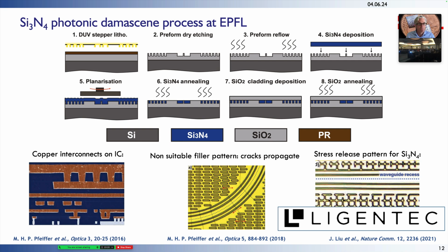Yeah, I mean, in theory. If you etch all the way through, you always see a limit. I didn't put it in the slides, but we have detailed this in papers that we published, very detailed follow-ups from Martin Pfeiffer, who developed the process in my group, in some of the references even here. Indeed, there's a limit also because of the conformal nature of the deposition. That's absolutely correct. But the highest we've done experimentally is 1 micron waveguide thickness for mid-IR waveguides.